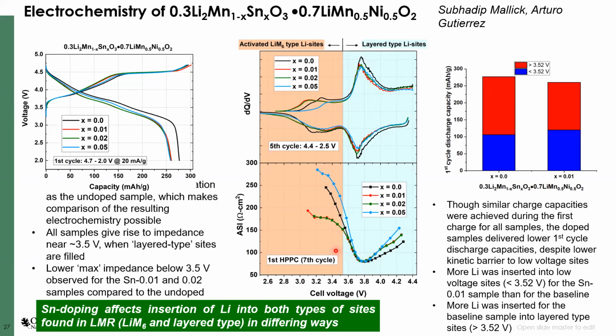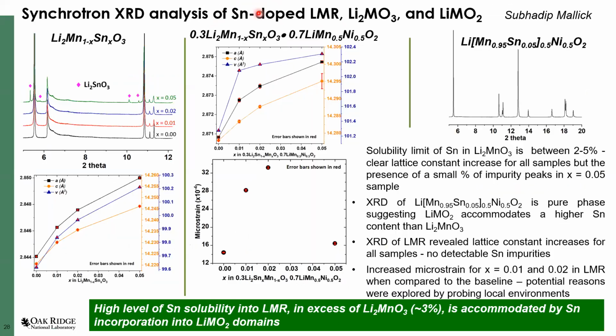So we chose tin because we know, based on the chemistry of tin in these lithium-rich systems, that tin would essentially go to this region which is lithium and manganese rich, and not go to these regions which do not have excess lithium. So we wanted to show that this is exactly what happens with this material, and we did a bunch of characterization. First and foremost, we did high-resolution synchrotron diffraction, and we were able to clearly show that the tin, for very small amounts of doping, goes into the lattice. However, an interesting thing that we found is that for low values, the microstrain that is induced becomes quite high. And we believe that is actually a good property to have for some of the electrochemical aspects.